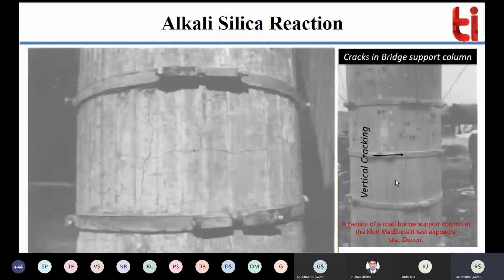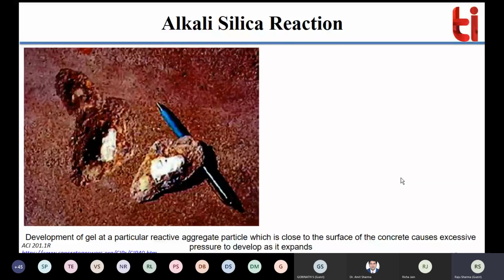It means that if your structural element is not subject to stresses and it is affected by the alkali silica reaction, that will create a map type of cracking. But if that structure is subjected to stressing, it will not create map cracking, but cracks which run along the directions of those stresses. So this is a difference in identifying alkali silica reaction, and this is the pop out.